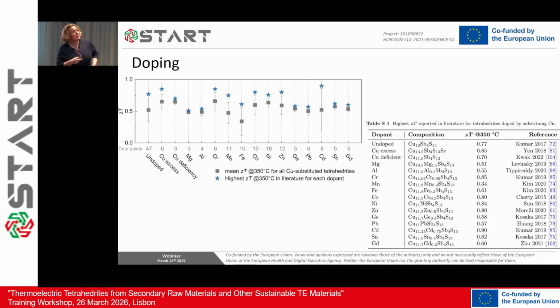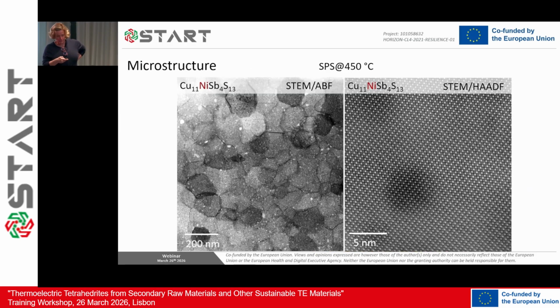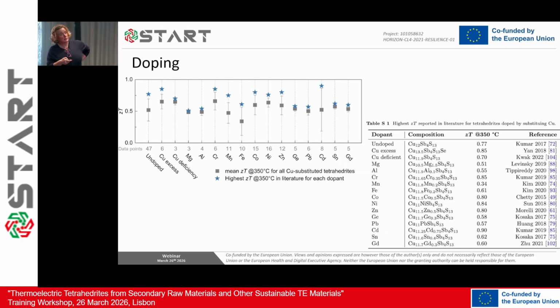I'll show you—here is the doping conclusion in terms of the elements. If you have all the elements plotted here, you see, for cadmium there are only 2 papers, so the statistics are very low. But in these other cases there are more papers, more studies, and there's something very striking: when you replace with 3D metals, transition metals, you see—this is the undoped, this is the best undoped, this is the average, and this is the standard deviation.